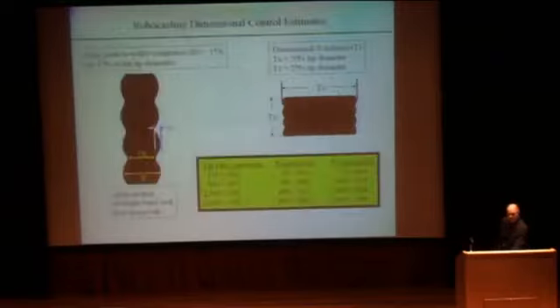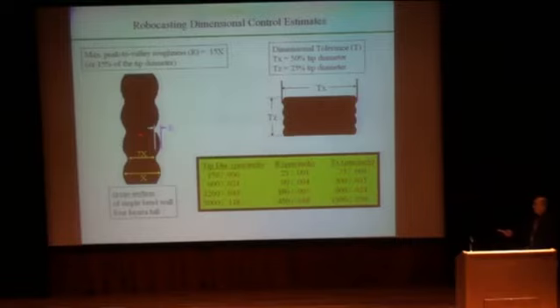So let's look at the characteristics, though, and some of the realities of this situation. We are putting this down bead by bead in layers, and no matter what you do, you're going to have some microscopic defects between the layers, but you're also going to have this irregularity on the surface. This irregularity is going to scale up with the size of the bead that you deposit. So typically, about 15% of the diameter of the bead is going to be your roughness. So if you're working with really small tips, really small nozzles, 150 microns, yeah, you can